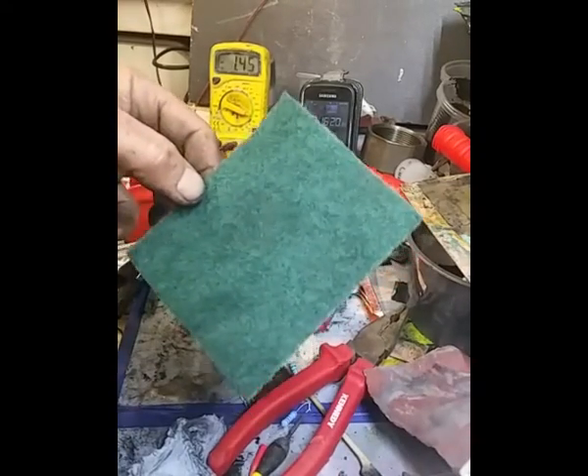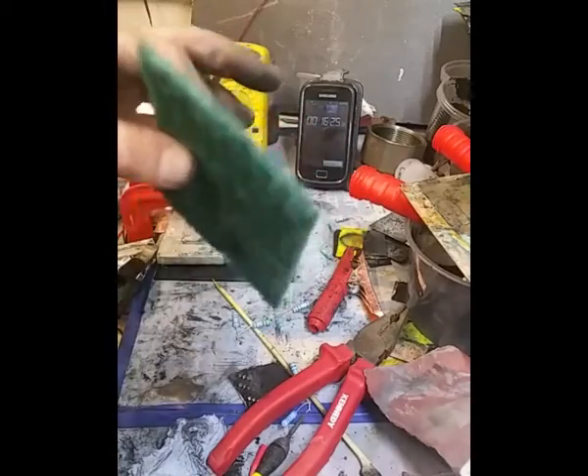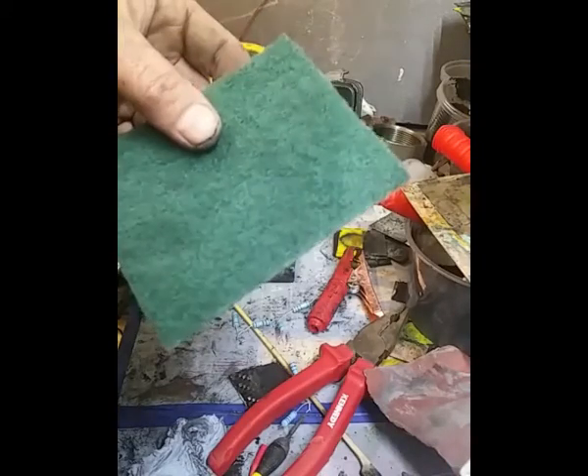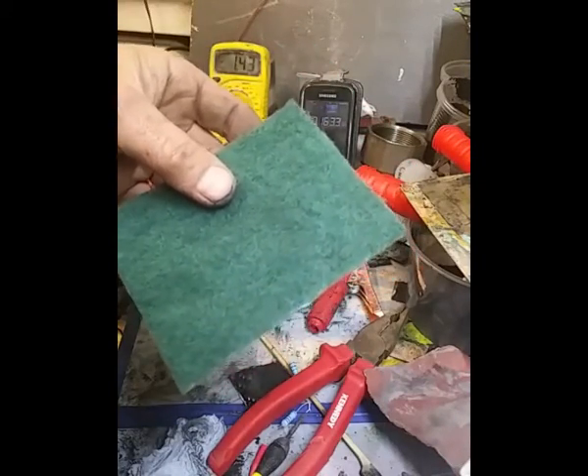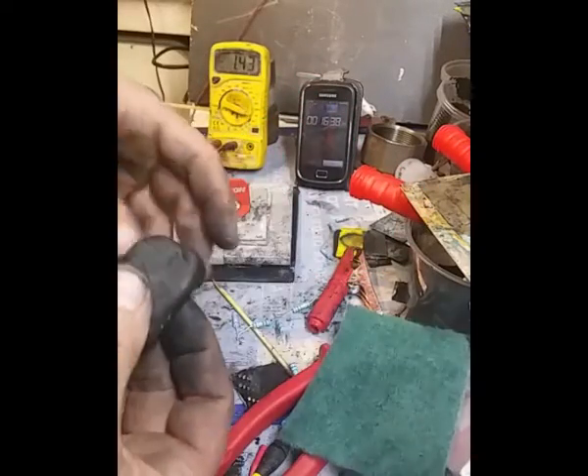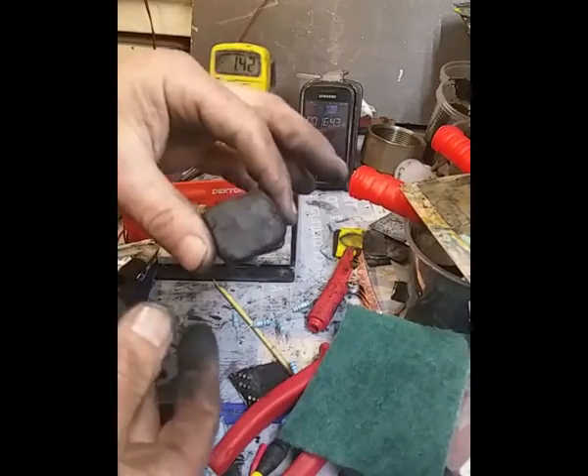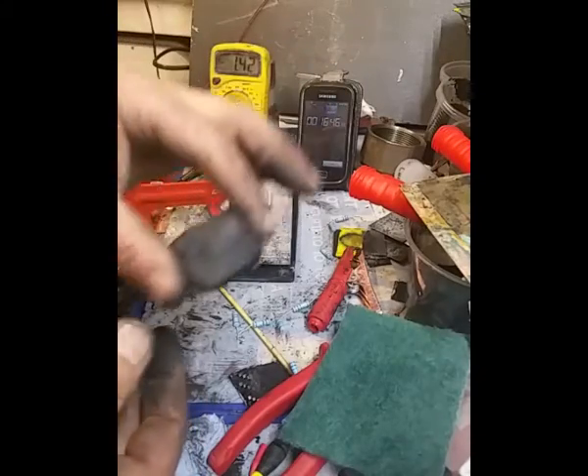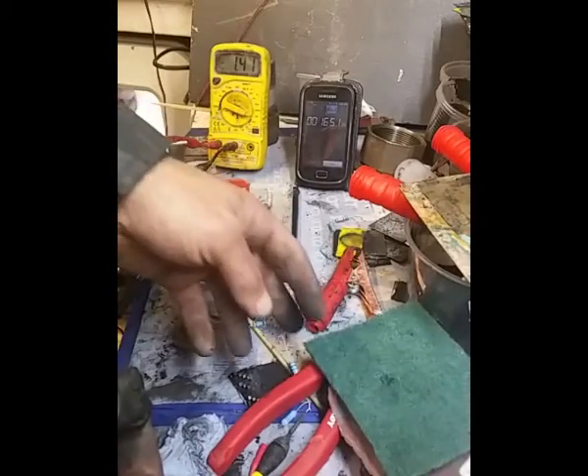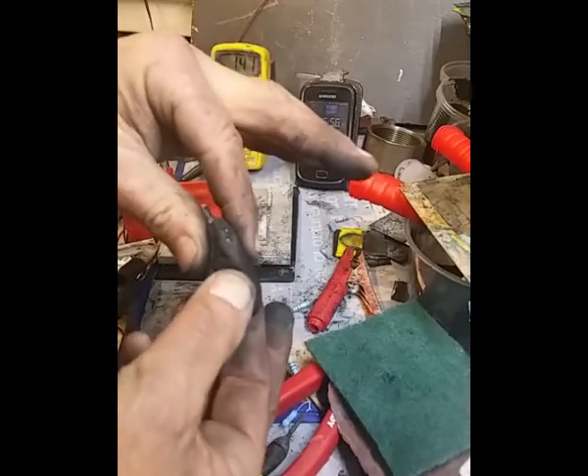I don't have to use this soft plastic material. It was a nice idea — if we were talking graphene it would be a different story with surface area — but because it's activated carbon, I think you need as much of the activated carbon capacity as you can get, and this material would take away a lot of that capacity. So yes, I've got it to work, but this foam approach is better — this is where I want to be.